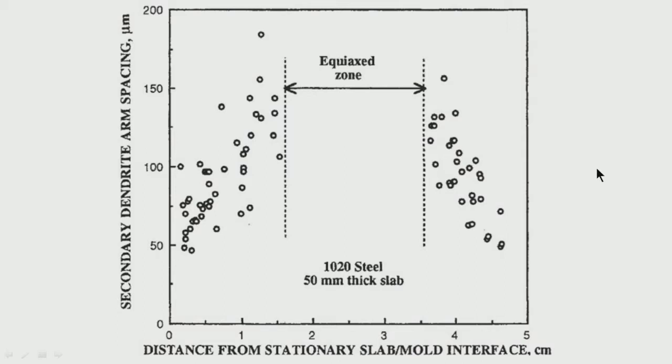That is not desirable, because the coarseness of the structure goes on increasing as you are going inside, and at the final central location you have very coarse structure, too much segregation, too much porosity. So, that area is really bad in quality. Central quality is bad because of high segregation, high porosity, and high solidification shrinkage. So, you require a good structure.